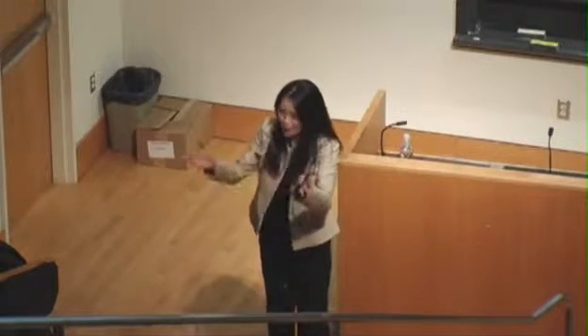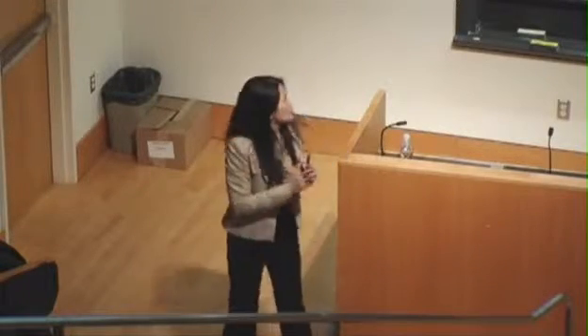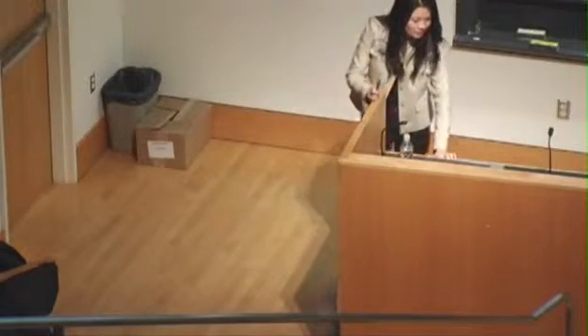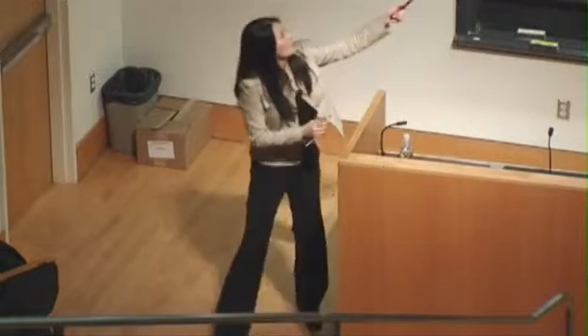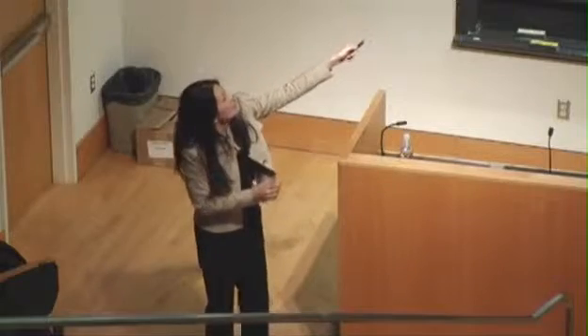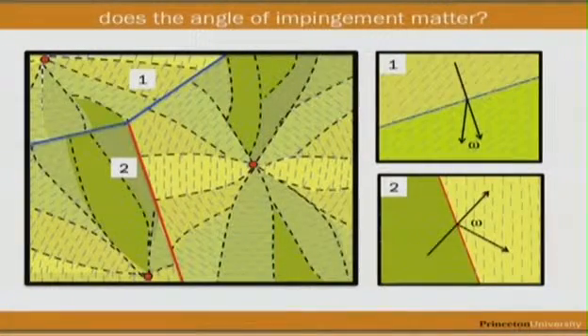Plus, a spherulite is not, if you think about a single crystal, you know how the molecules are exactly oriented within a single crystal. A spherulite is not a single crystal per se. There are lots of low-angle grain boundaries in it, right? So if I go back to this cartoon, if you look at how the molecules are oriented, there are slight variations in the angle the molecules are oriented. So this is actually a low-angle boundary. So there are lots of low-angle boundaries within a spherulite. So that limits the mobility too.